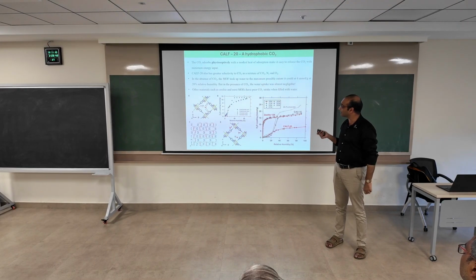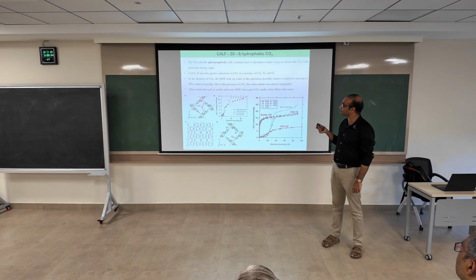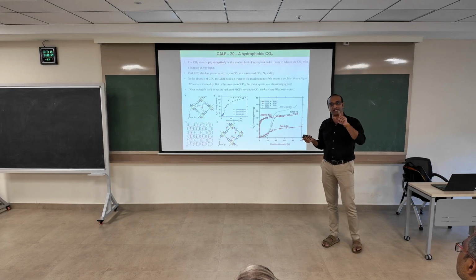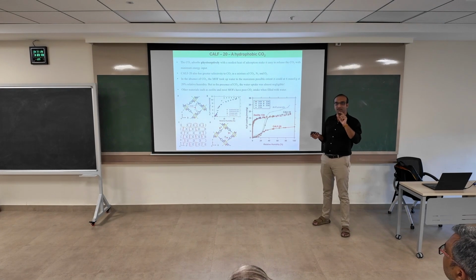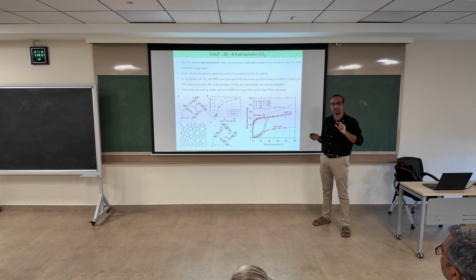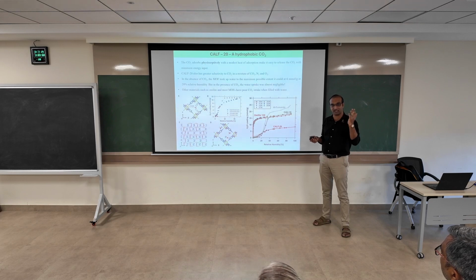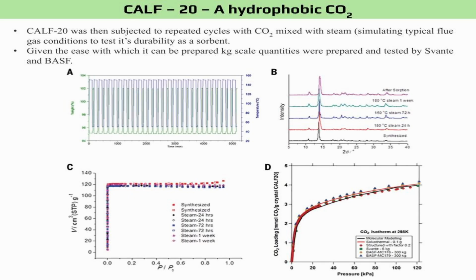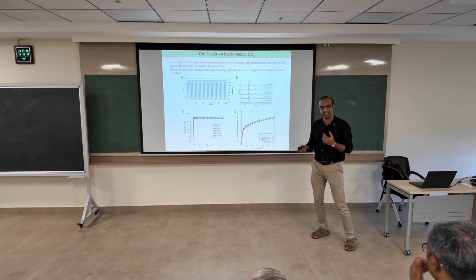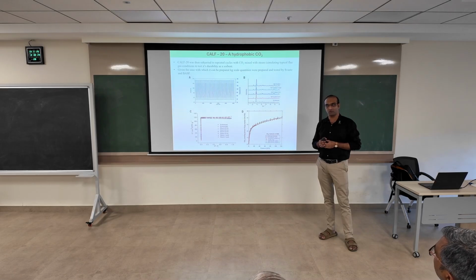So one of the advantages, the reason why it's been commercialized so fast, is it fits all the criteria of a good material that reduces the energy demand, quickly absorbs and desorbs CO2, and can be very stable for long conditions underwater. Even if you put large amounts of steam, it's stable. They did the test on this, and they repeated it through many cycles. Okay, they did steam for 24 hours, 72 hours, 1 week. The activity stayed the same. Okay, its ability to capture the CO2 in the presence of water was very stable.